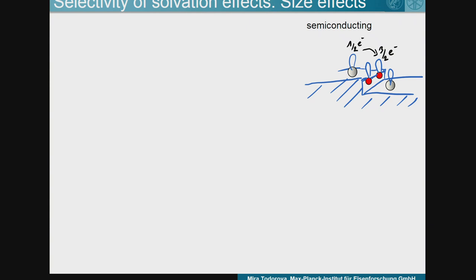Now, within these triangular reconstructions, we do have edges which are decorated with oxygen atoms, while the terraces have zinc atoms. And if you remember, the oxygen atoms have 3/2 electrons per dangling bond. Zinc atoms have 1/2 electron per dangling bond. So it would be easy, if they are close by, for an electron from the zinc dangling bond to go to the oxygen dangling bond, thereby ending up with a situation where we don't have charge at the surface if we have the same number of zinc and oxygen dangling bonds.